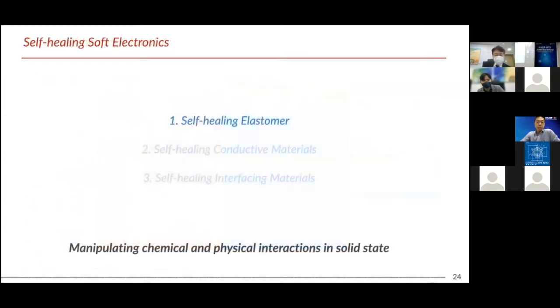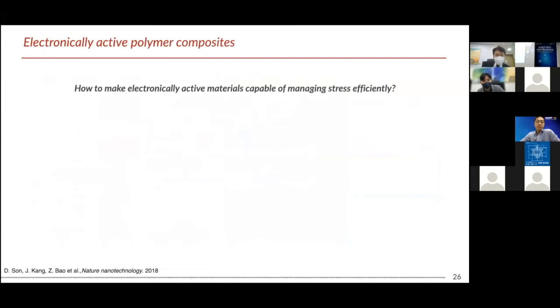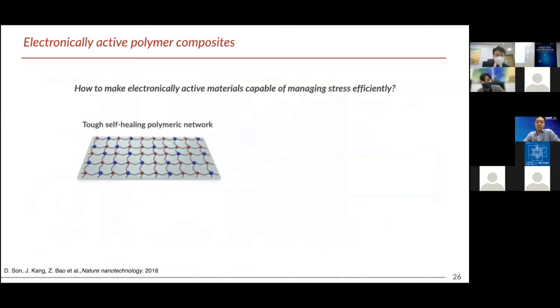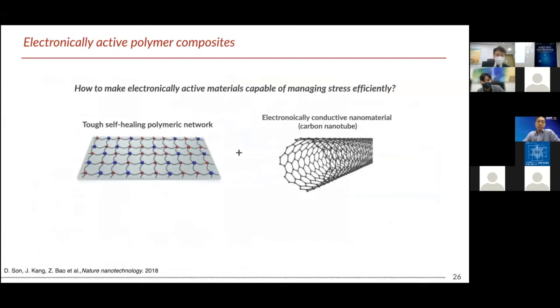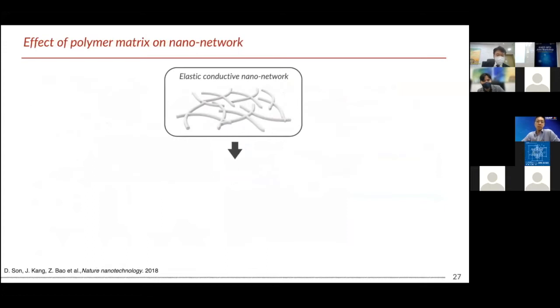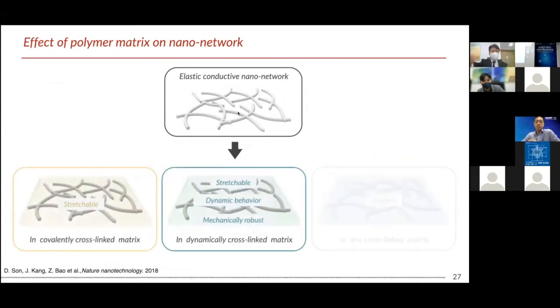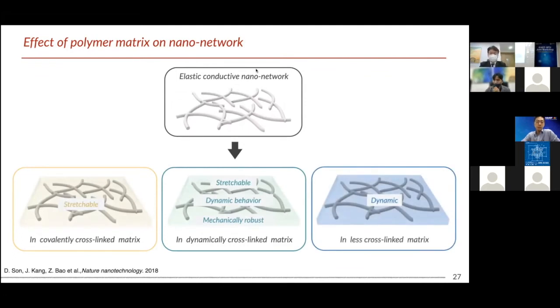Then I would like to move to the second part, about how we can make self-healing conductive materials. Basically, the easiest way to make a conductive material is just adding a conductive component into the polymer matrix. Our initial motivation was that we were very curious whether, if we embed this kind of 1D nanowire-based conductive nano network, it can change its behavior depending on the embedding polymer matrix. So we embedded this CNT or silver nanowire-based nano network into a fully cross-linked elastomer, a self-healable polymer matrix, and also a gum-like polymer matrix.